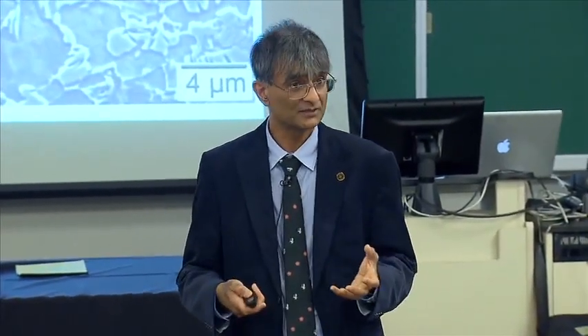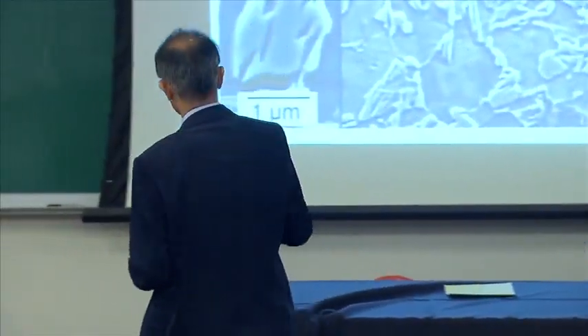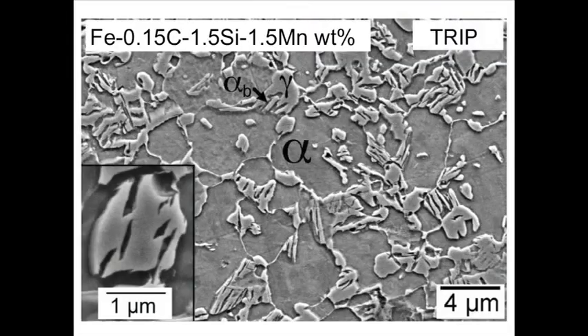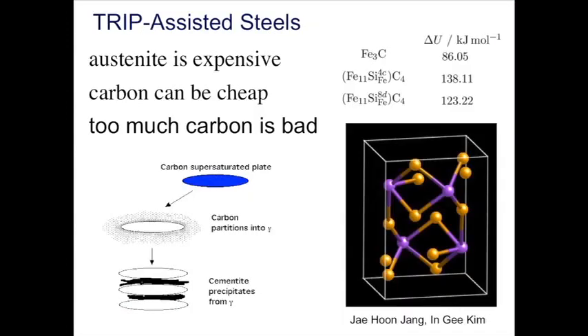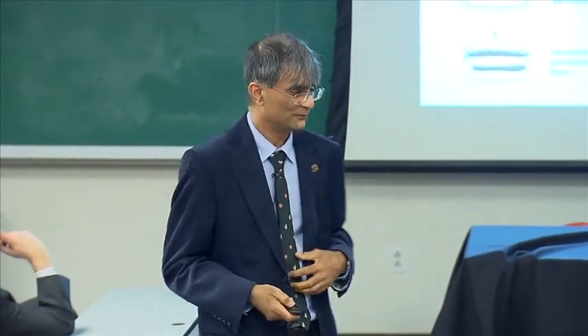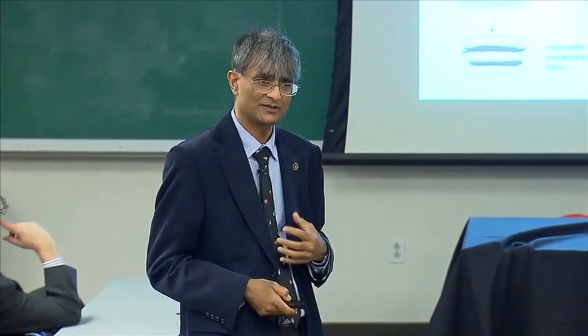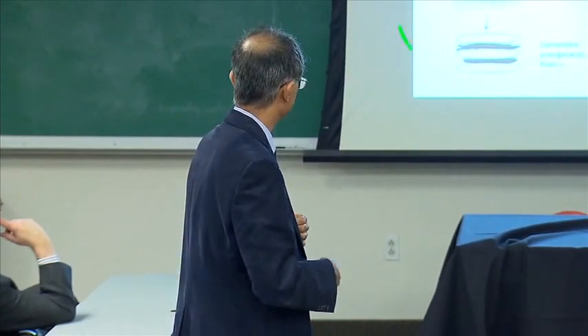You can't get a cheaper alloying element than carbon. In fact, during steel making, you remove the carbon from the iron that comes out of the blast furnace. So this is called a TRIP-assisted steel, and it has a very simple composition, and notice the silicon. Now, as Professor Lewandowski said, bainite is my favorite topic, and I've worked on it for about 40 years, and I'll summarize all that in one slide here.